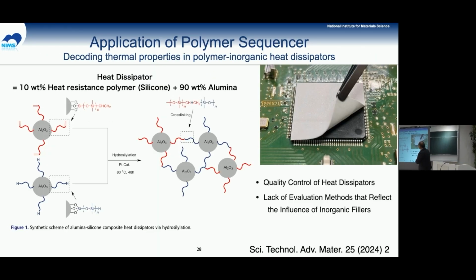Also, another example here is an application of the polymer sequencer in composite materials. As I told you before, our method can be applied to inorganic materials, composite materials with inorganic materials. As a demonstration, we applied our method to understand the performance of heat resistance polymers. These usually require good heat resistance as well as adhesion to the substrate. However, almost 90 weight percent of these materials is alumina, almost no polymers. Only 10 weight percent is silicone.